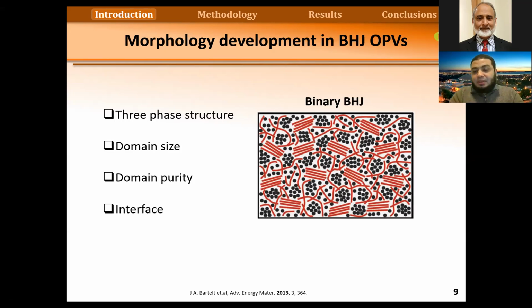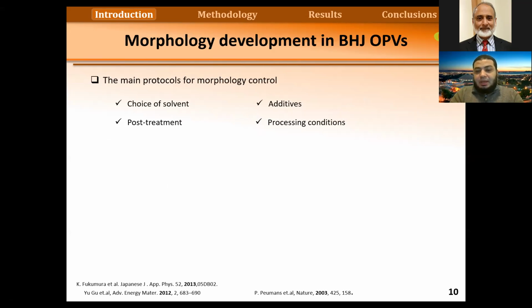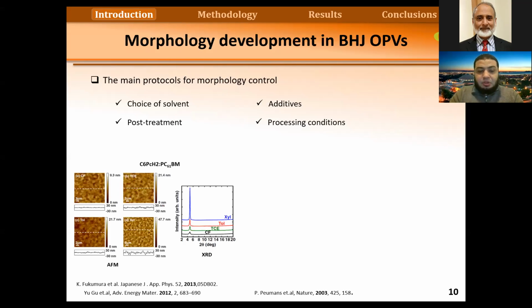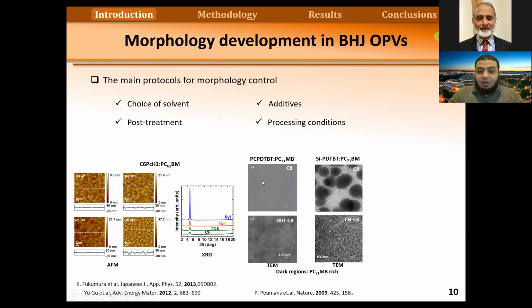So we need to control this morphology by using some processing techniques. Usually people use a specific solvent. The choice of the solvent will affect what this morphology looks like. We can see here that if we use different solvents, we can get different phase separation between donor and acceptor material. Also, we can use different additives to manipulate this. Some additives can increase the phase separation or can reduce it. Like in the one on the left, the donor and acceptor domains are mixed.